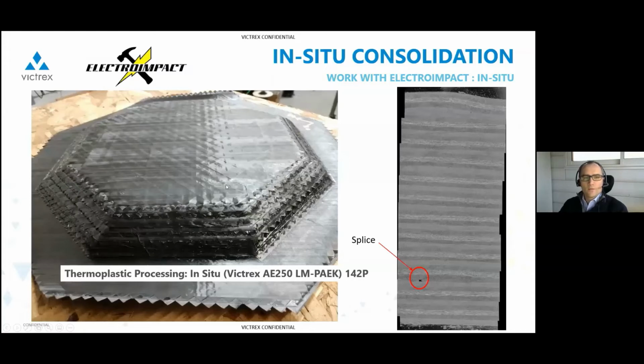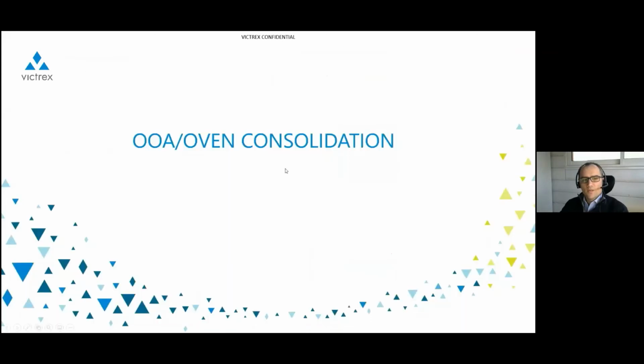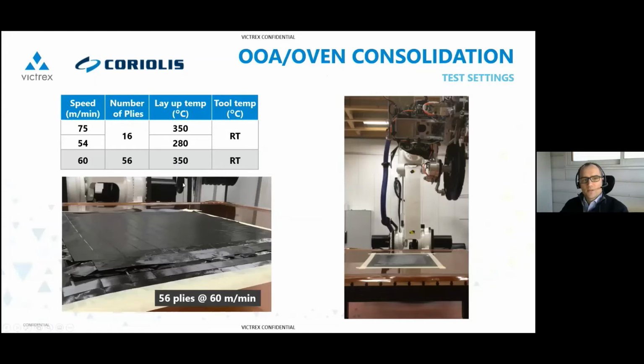So the next step is about out-of-autoclave and oven consolidation. Likewise, we worked on this topic between Victrex and Coriolis, and we set again a series of parameters, and here we wanted to push the boundaries and try to achieve high layup speed. From a previous study with Coriolis, we had already set the baseline of 60 meters per minute. That's really the head speed, the layup speed.